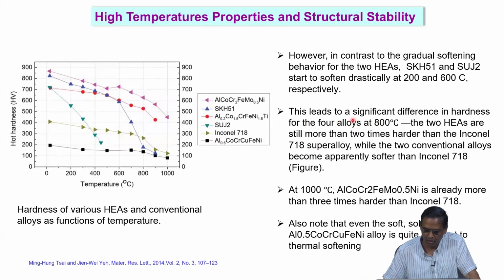This leads to a significant difference in the hardness for the 4 alloys at 800 degrees centigrade. The 2 high entropy alloys are still more than 2 times harder than the Inconel 718 superalloy, while the 2 conventional alloys become apparently softer than Inconel 718. So at 1000 degrees, the high entropy alloy is already more than 3 times harder than Inconel 718. Also, you can note that even the soft single FCC high entropy alloy is quite resistant to thermal softening. So these are some of the interesting results comparing the conventional alloys, showing the superiority of high entropy alloys with higher resistance to thermal softening.